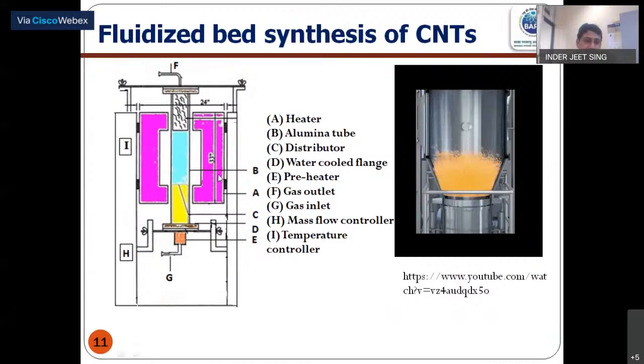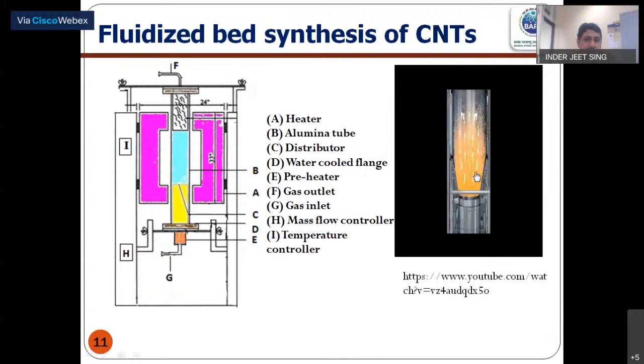So what happens? This is a typical fluidized bed furnace, where you can see the blue color. There is the main reaction chamber. There we put the carbon black, and this yellow color is a distributor from where we pass the gas. I'll just show a video which I have taken from the internet, showing how fluidization happens. If we pass a gas like argon, then this carbon black starts fluidizing in this fashion.